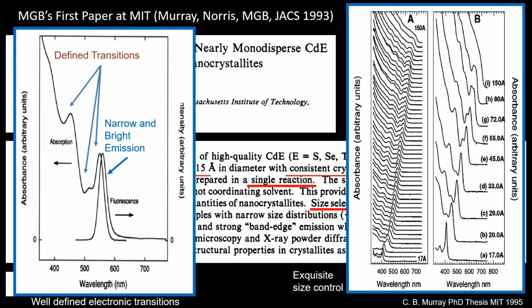And this graph from Chris's thesis shows the control that this very simple process had on the size of the particles. So the difference in size between the sequential spectra that you see here, as you march from something that looks bluish with an absorption of 400 to a very, very dark red for the 15 nanometer particles on the very top, the difference in size between those is just tens to 20 atoms, really. They just added to it. So you have this exquisite control over the particle dimensions.